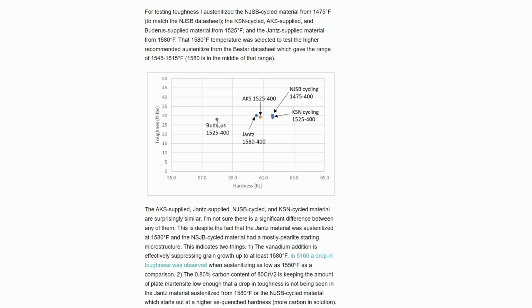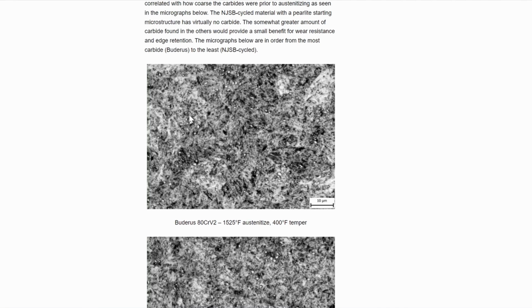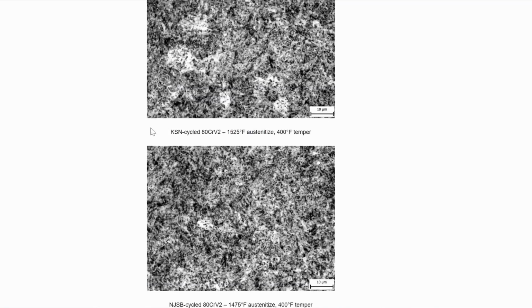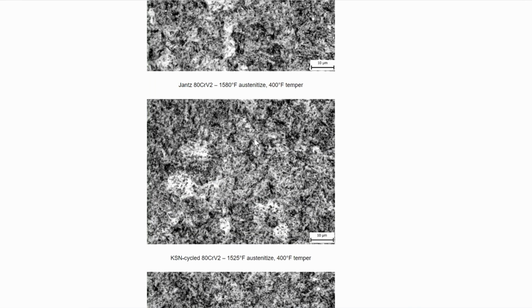So should you thermal cycle the steel to get something more like this than like this? It's totally up to you. I mean, these properties aren't terrible. It's a little soft. You can compensate with the heat treatment, but then the toughness may go down some. However, you do get a bit more carbide. You can see these little white particles. There are more carbides in this material than when you use my cycling, where the carbides are much smaller and there's a smaller volume of them.